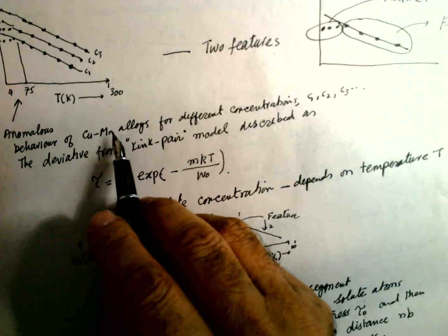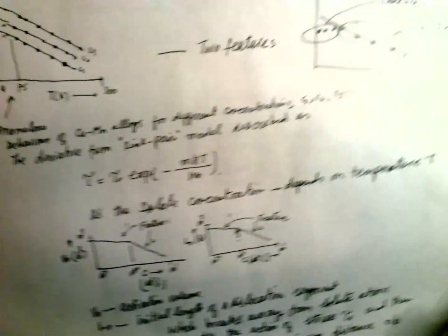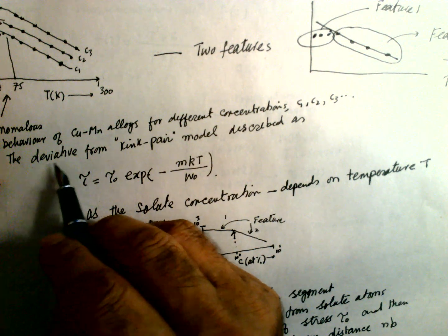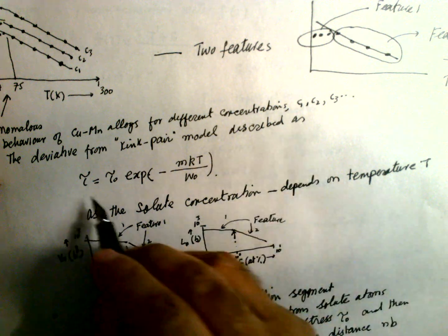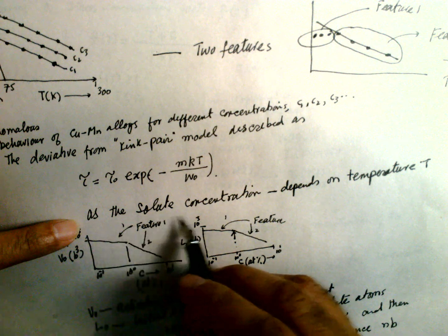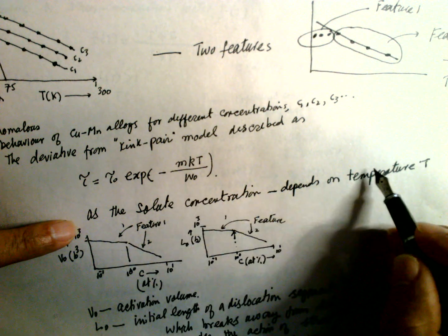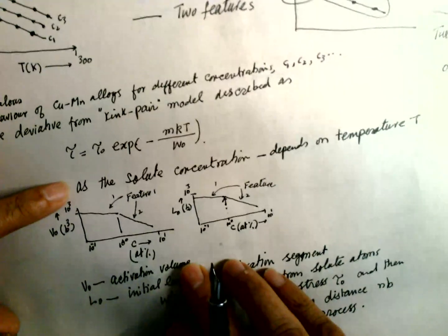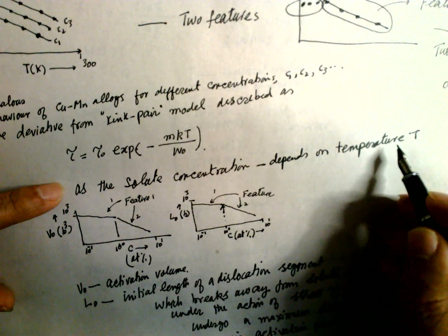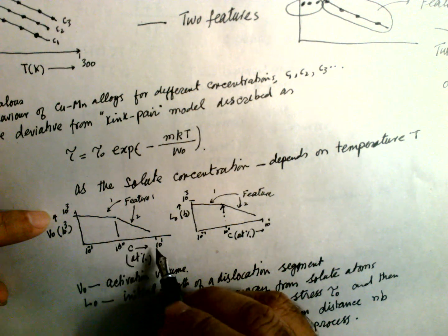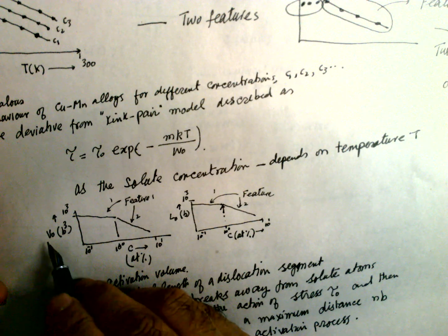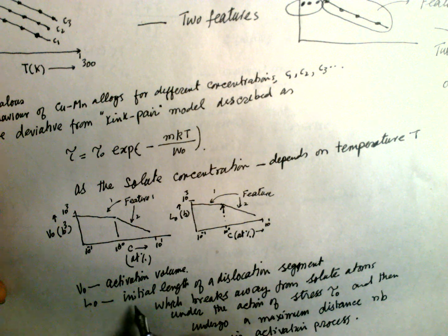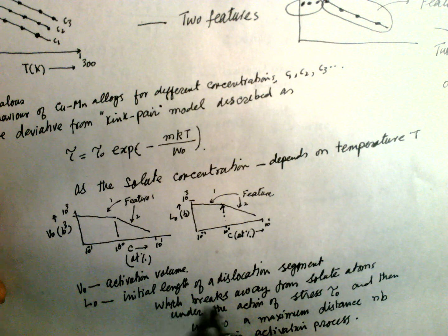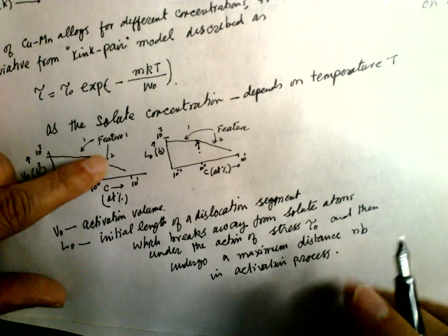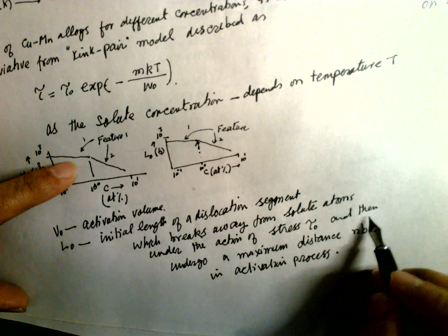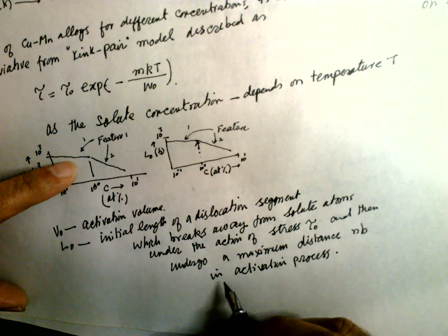So the anomalous behavior of copper manganese alloy for different concentrations C1 and C2 is explained. The deviation from the kink-pair model is described by this expression. In the kink-pair model the solute concentration is independent of temperature, but it has been established that the solute concentration depends upon the temperature T. These two figures describe V naught and L naught. V naught is the activation volume, and L naught is the initial length of a dislocation segment, which breaks away from the solute atoms under the action of stress tau naught, and then undergoes maximum distance in the activation process.